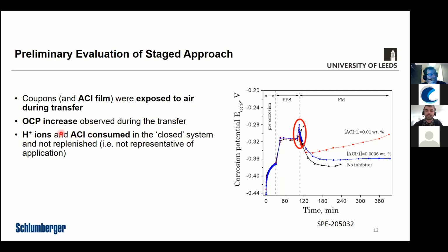Similarly, the corrosion inhibitor is also used up and changes essentially the availability of inhibitor within the beaker that those experiments are completed in. So we would term that to be a closed system, essentially being that the species, the molecules, are not replenished. And if you were to consider a pipe flow environment, that wouldn't be representative or realistic of the environment that would be seen in the field, where you obviously have a continuous flow of a particular fluid, which will have essentially the same sort of chemistry flowing across the carbon steel pipe or tubing, whatever, at any given time during the injection procedure.